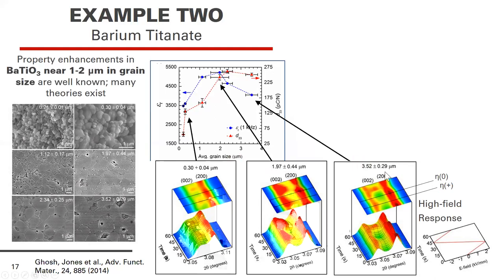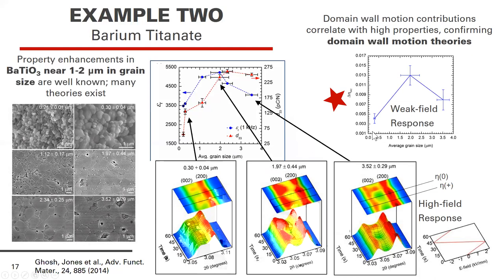We also did a weak field experiment. And without getting into too many more details that go beyond one slide, if you plot the degree of domain switching, eta, as a function of grain size, you can see that it maximizes at this intermediate grain size. And so we hoped that this contribution would add value to domain wall motion being one of the most important contributors to this high response.